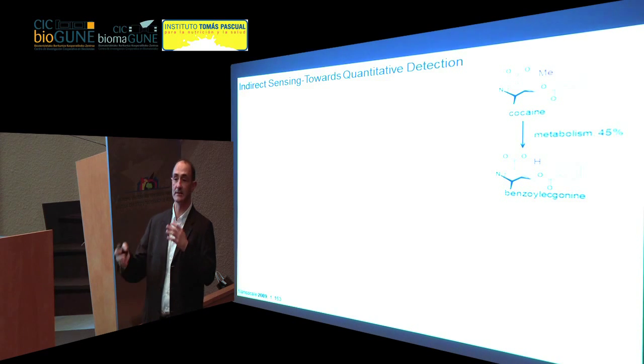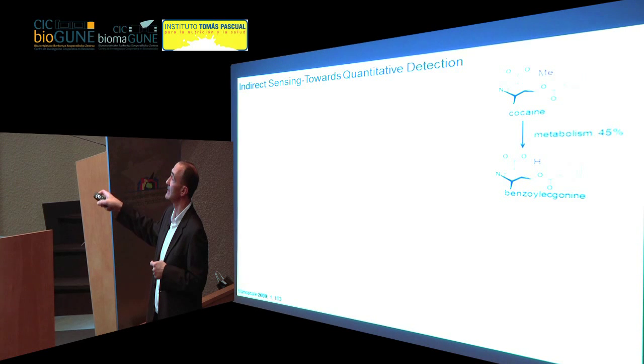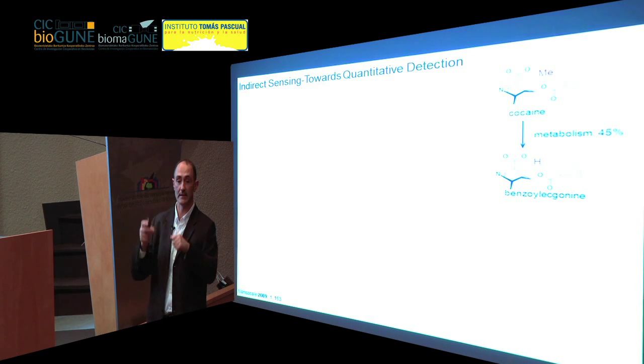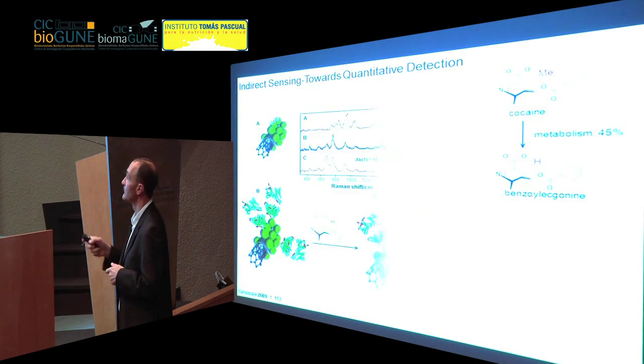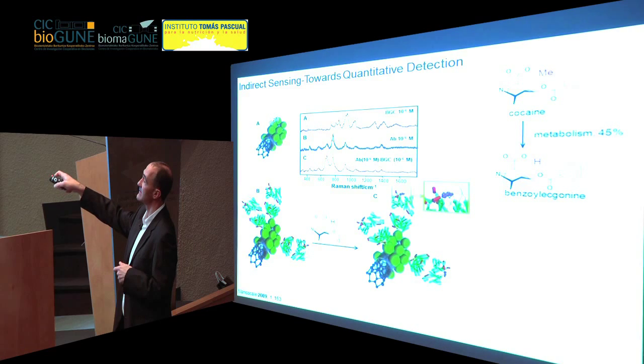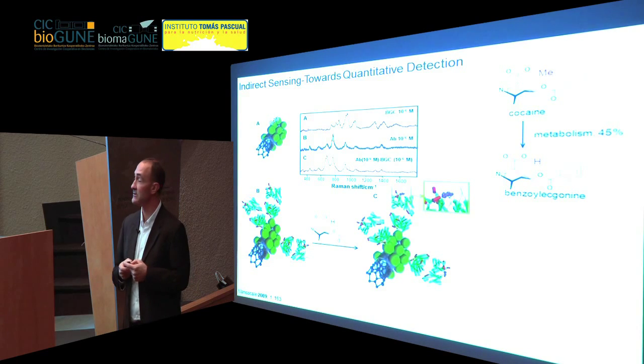So we went into the literature, we found that cocaine is metabolized into a few different types of molecules. One of the most abundant metabolites is this one, benzoylecgonine. This molecule coincidentally has a nitrogen here that might be able to attach to the metallic particle, so we could try to do direct identification of this molecule, and we can indeed recognize the surface enhanced Raman scattering spectrum of benzoylecgonine down to micromolar concentrations. But we decided to do a selective detection, which might actually help us to quantify the concentration of this analyte.